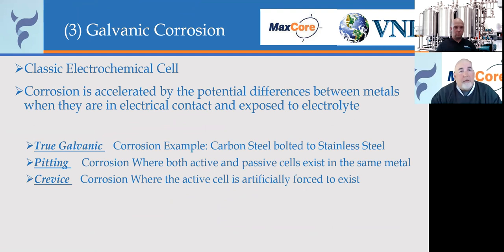That is a classic electrochemical cell that is accelerated by the potential differences in the metals when they come in contact and they're exposed to electrolyte and they have an adjoining path. True galvanic corrosion is something along the lines where you have dissimilar metals put together, like a carbon steel bolted to a stainless steel, for instance, where stainless steel is going to be more cathodic than your carbon steel. Pitting is corrosion where both active and passive cells exist on the same metal. And crevice is where an active cell is artificially forced to exist. And we're going to kind of look at those.